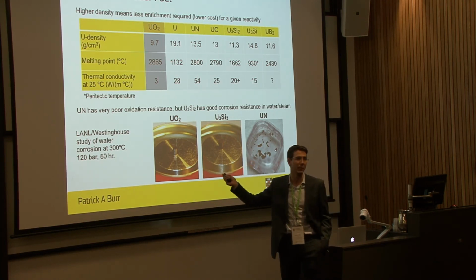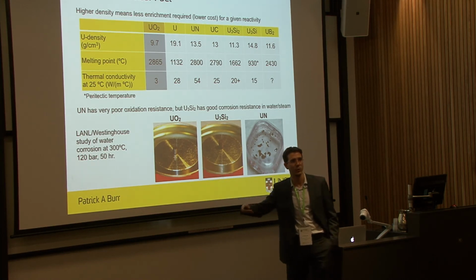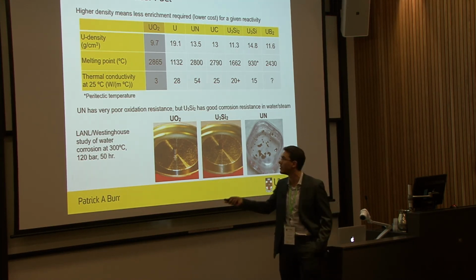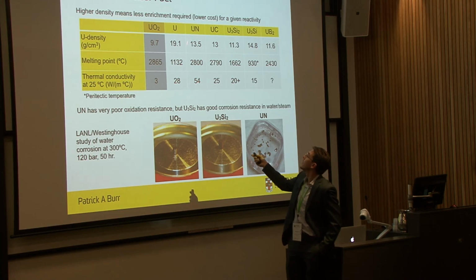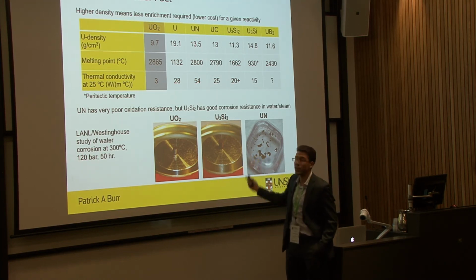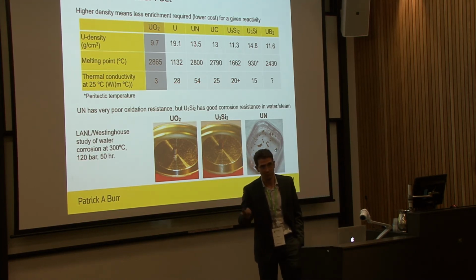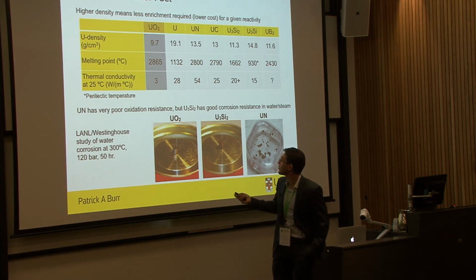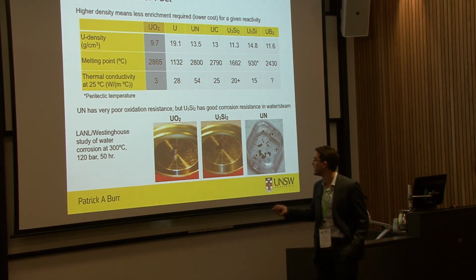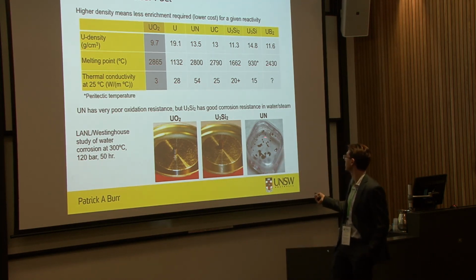and I'm cheating slightly because I'm only showing you the room temperature value. It does get worse as you increase the temperature of the material, but it's still very good. And the uranium density is actually very, very high. So it looks like an amazing material, and it is on paper. It's got the very bad downside that it has very poor oxidation resistance.